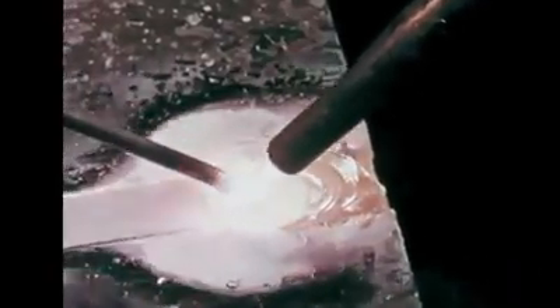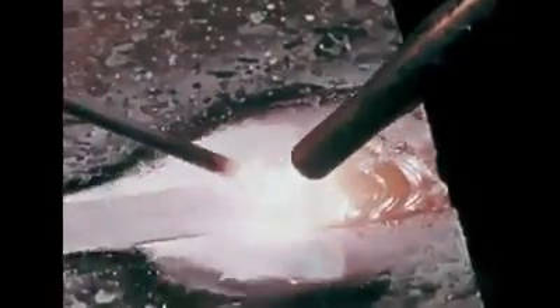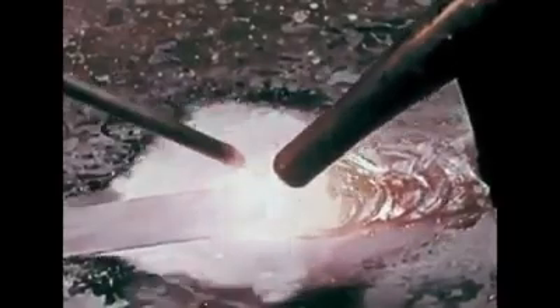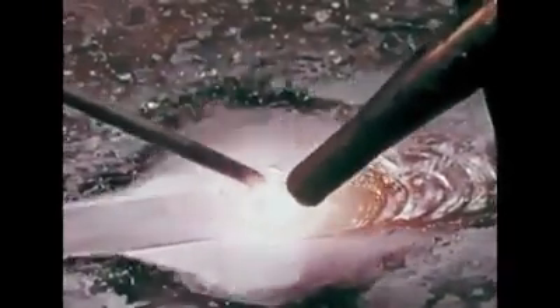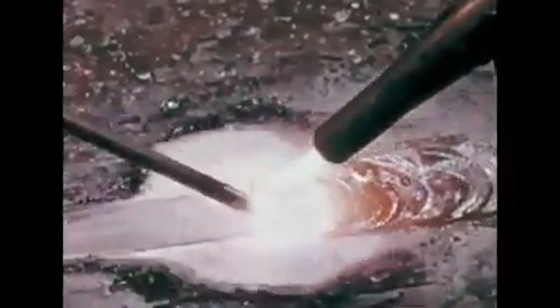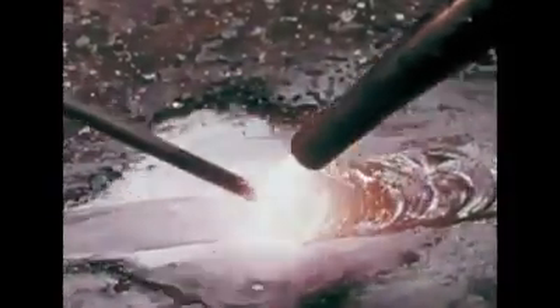Use the welding rod and the flame to move the puddle along the V. Notice how the sides of the V become molten ahead of the advancing weld puddle. By directing the flame more on the rod than on the puddle, you can prevent the puddle from becoming too fluid and difficult to control. Proper control of the weld puddle comes with practice. Control puddle movement with the flame and the welding rod. Remember, the puddle will flow naturally in the direction that has been heated.